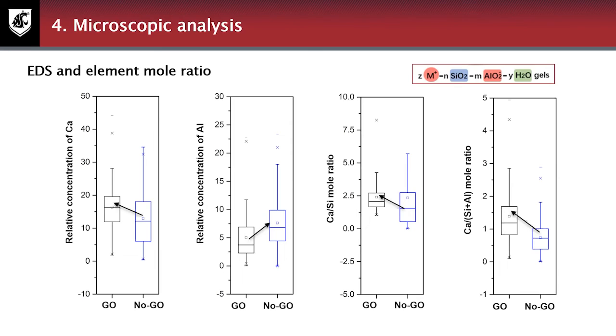Based on the model on the top of this slide, the M is the alkaline element. So in this study, it should be the calcium. So the increased molar ratio means that Z, the coefficient of M, was increased. The meaning of Z is the degree of polymerization. So here we can summarize an important conclusion that graphene oxide increased the degree of polymerization of the hydrates.